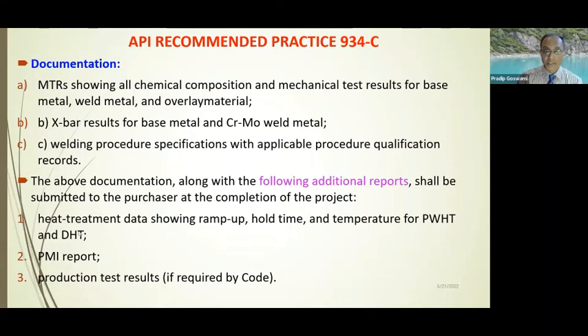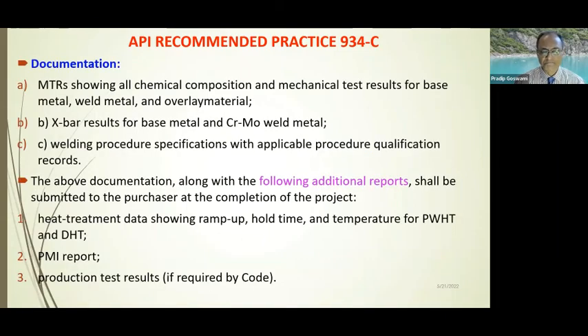And those typically include heat treatment data showing the ramp up, hold time, and temperature, and that is required for the post-weld heat treatment as well as for the DHT. The PMI report for all the welds, including the weld overlay as well as the base metal also. And the production test results, that is the PTC, if it is required by the code. So in a nutshell, I ran through this recommended practice, that is 934-C.